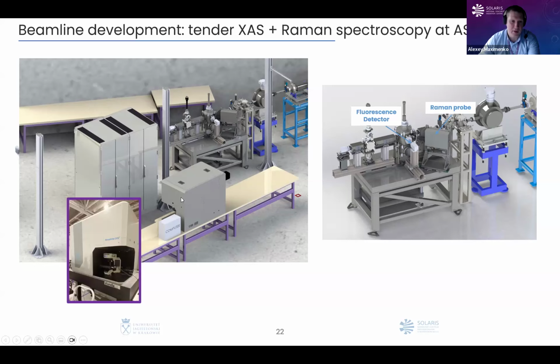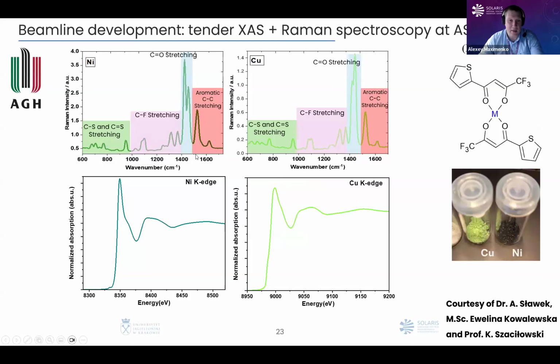What is also important is that this microscope is an independent device. It means that even if your sample gives a very small and not intense Raman signal, which could not be used for providing simultaneous Raman measurements, because as you can see, Raman signal is much less than the infrared signal which you can get in infrared spectroscopy, not every sample could be measured in such a combination of XAS plus Raman. But nevertheless, we can take the same sample, put it under the microscope, and investigate its vibrational structure. It means that when you measure at our beamline, we could provide you with data from two spectroscopies, Raman spectroscopy and XAS.